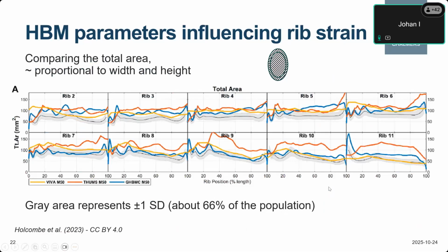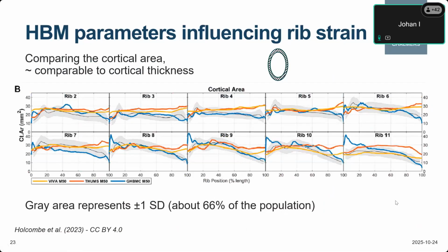So this is an indication that maybe the width and the height is a bit on the high side for the THUMS model. And in this case, I can also say that the gray area represents plus minus 1 standard deviation, so about 66% of the population. So we could make it twice as big, and then we have 95% of the population, which is a reasonable number to compare to, I think. If we look at the cortical area, I would say that the models are quite good here. The lower ones are more or less inside the corridor, most of the upper ones as well. So all of the models, or at least the GHBMC and the THUMS, because we cannot really compare the VIVA Plus, probably have a decent representation of the cortical thickness here.